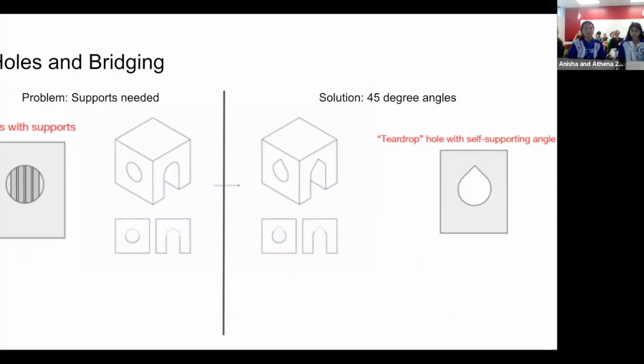So speaking of bridging, PLA is really good at bridging. Some other things here: how do you get around having supports? So when you're designing your part, you want to avoid supports. Like I said, the orientation matters, but also when you're designing it, there are little tips and tricks that you can add in to try to avoid those supports being generated. So anything at a 45-degree overhang angle, most slicing software, including Markforged Eiger, will automatically detect those and not create supports. So you can do this kind of teardrop hole on like archways or holes on the right-hand side, and that way you will not have supports. Supports can be a pain to take out. Occasionally those supports are unavoidable.